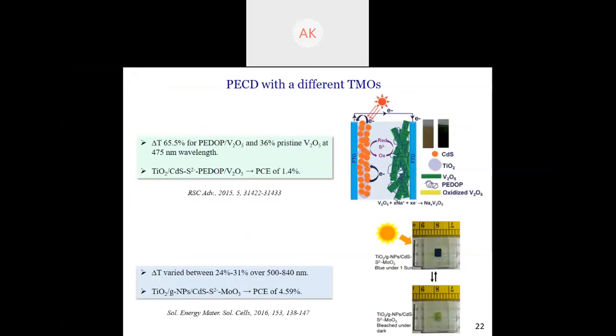So in my lab, there have been reports of PECDs which have been fabricated with different transition metal oxides. Firstly, we had tried vanadium pentoxide at 475 nanometer wavelength. It gave a del T of 36%. When we made a composite with PEDOP, these films gave a transmittance of 65.5%, which was pretty high. The power conversion efficiency of these cells was not very high. It was only 1.4%. We tried improving it in the following year.